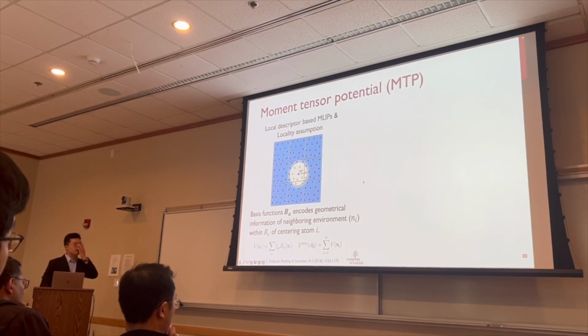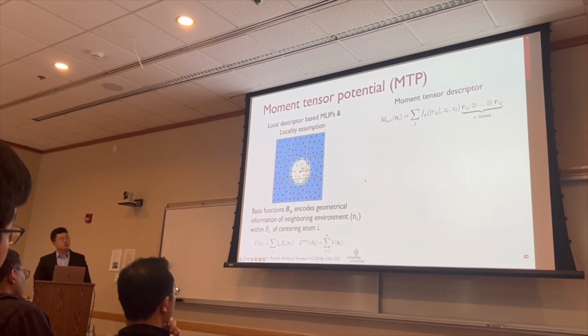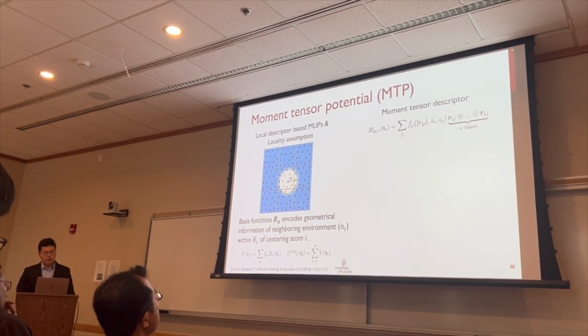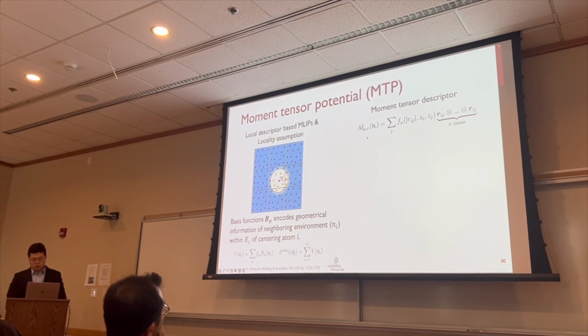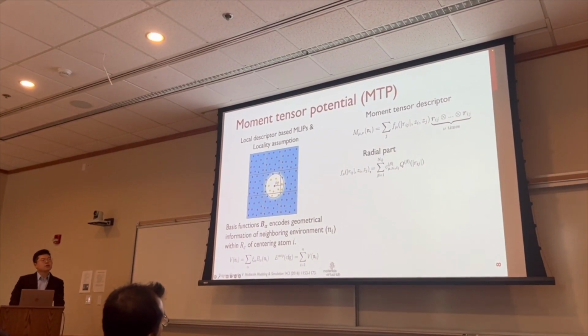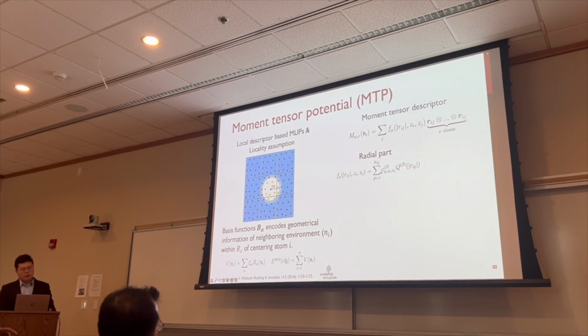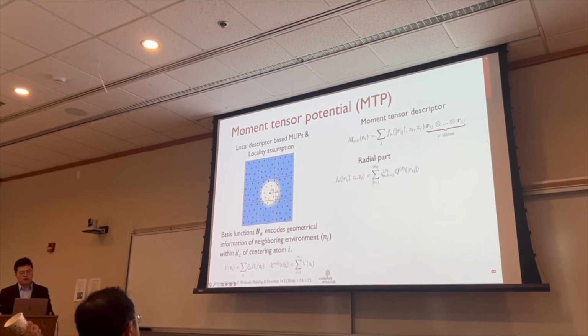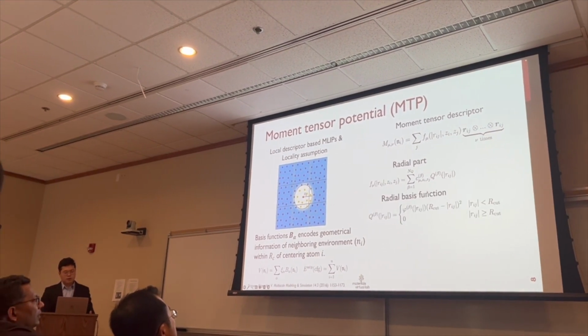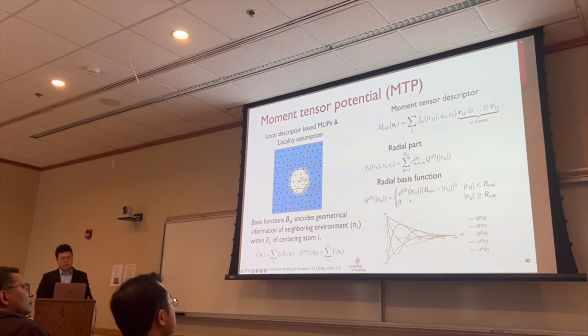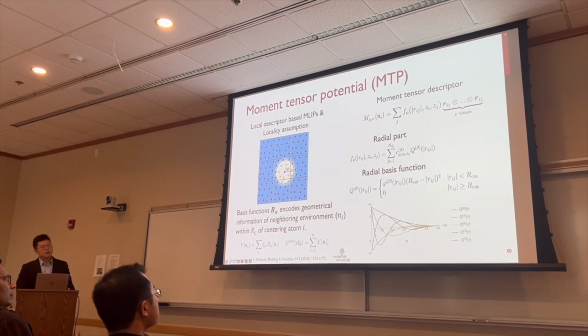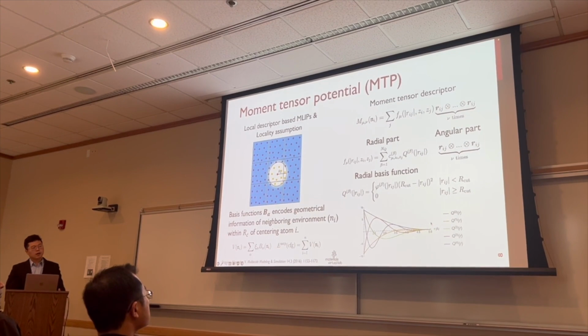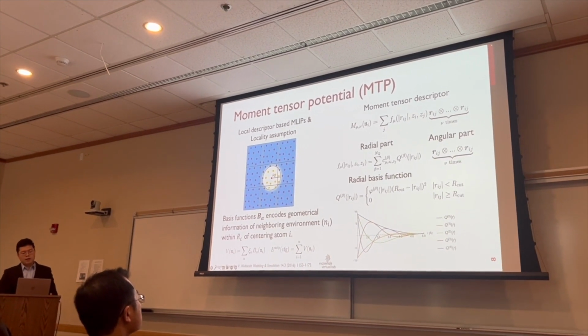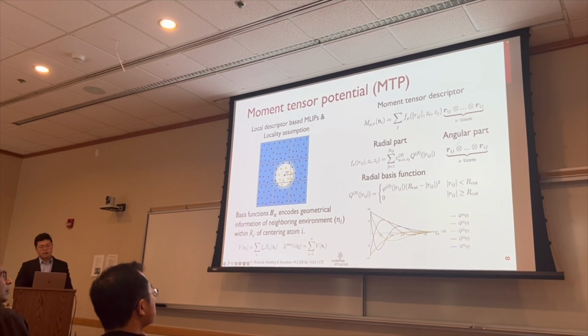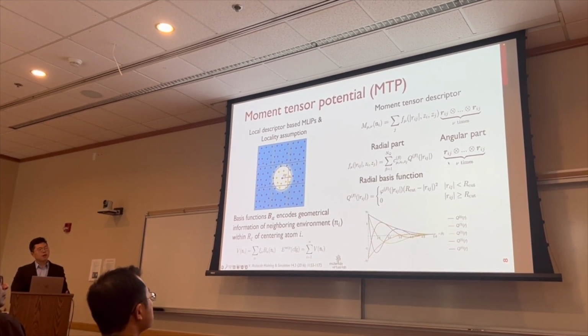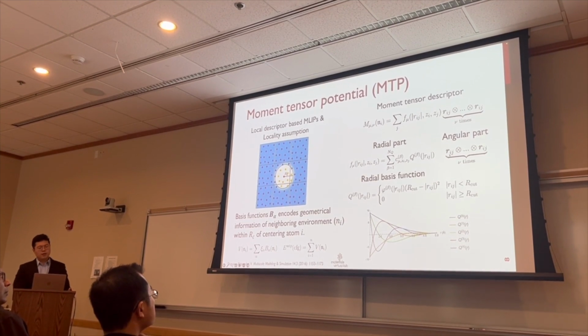Especially for the moment tensor potential, it defines this moment tensor descriptor to encode the structure information. In this moment tensor descriptor, we have the F mu, which is the radial part. That is a summation of the product of this trainable coefficient C with the radial basis function Q. And this radial basis function is defined this way so that it's smooth and it decays to 0 at the cutoff radius. And it also has this angular part, which is the outer product of the vector pointing from the center atom I to neighboring atom J.